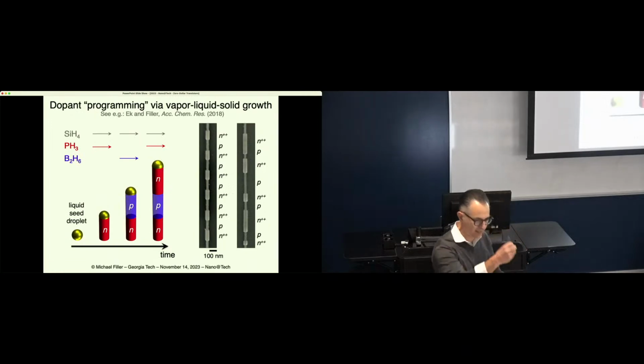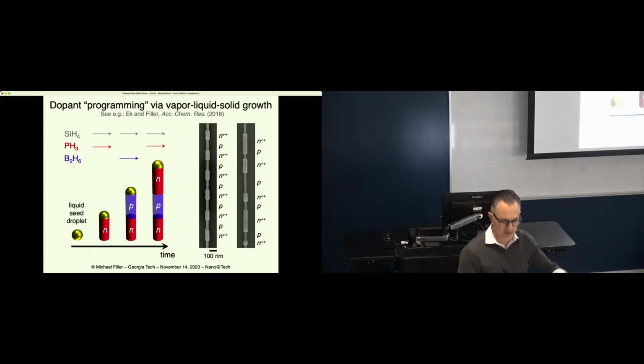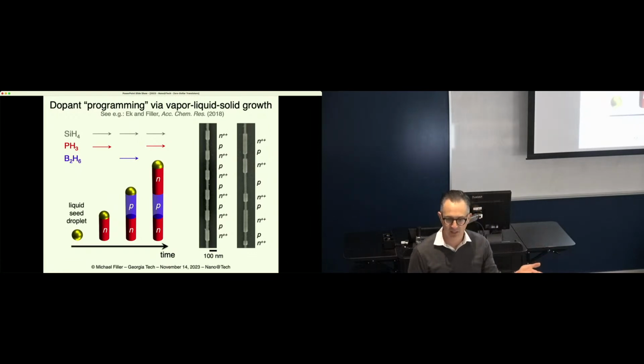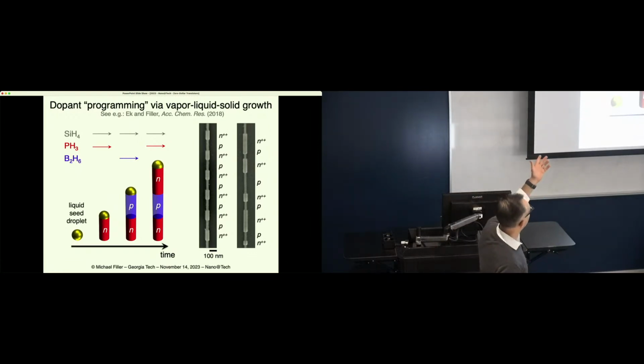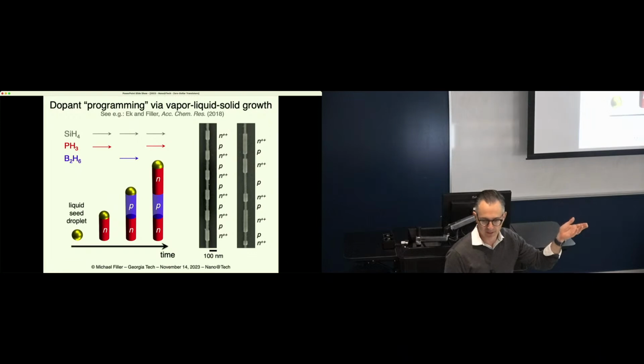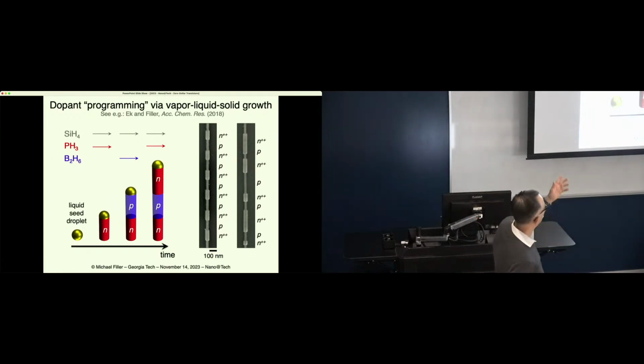This is a technique called the vapor-liquid-solid growth technique, where we start with a seed droplet and we deliver semiconductor precursors, here in the form of silane, from the vapor. So it's a CVD process. And we can co-flow with the semiconductor species dopants, so phosphine or diborane in the case of silicon, and we can, in time, control what we're flowing, and we can create source channel drain along the length of this crystal as it grows.